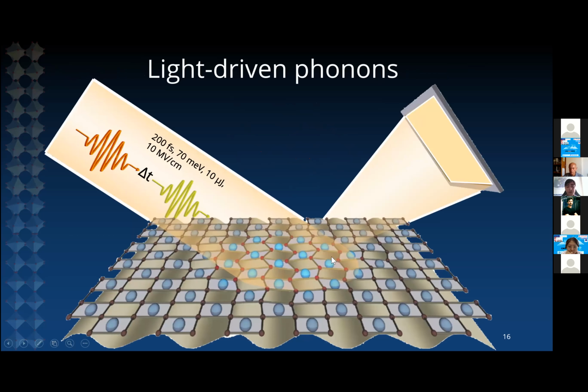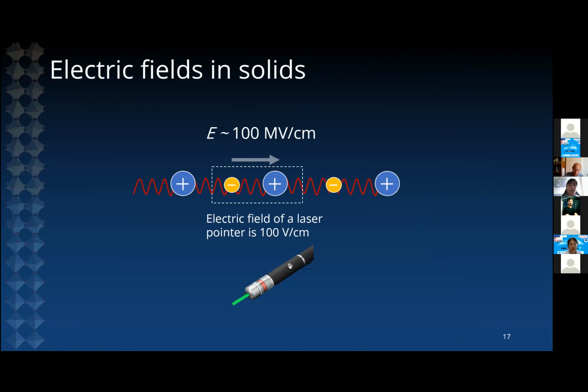So this was pioneered by the group of Andrea Cavalleri, and the concept here is to prepare pulses of laser light in the mid-infrared range that are tuned in resonance with a phonon mode. And in order to significantly control the properties of the material, we need to consider what are the interatomic electric fields that we find in matter. So the typical interatomic electric field in a perovskite material is of the order of 100 megavolt per centimeter. So if you want to significantly perturb atomic positions using laser light, you want to apply a mid-infrared pulse that has a comparable electric field.